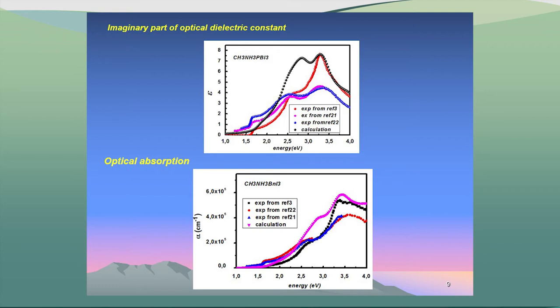We also calculate the optical absorption. Even if the shape is not very similar, the scale is correct, and is still correct comparing with the experimental data. This conclusion also holds for the optical absorption — our calculation is close to the measurements. The difference and deviation comes from the surface, because some surfaces have more roughness or more layers of humidity of perovskite.